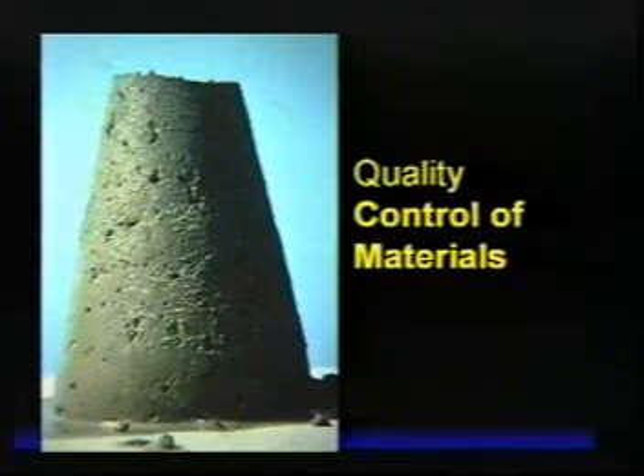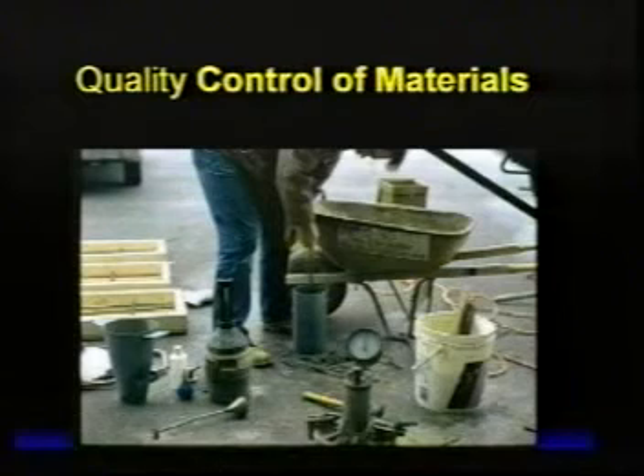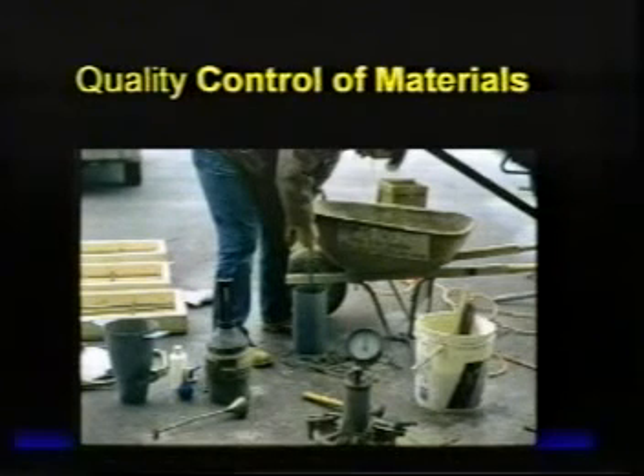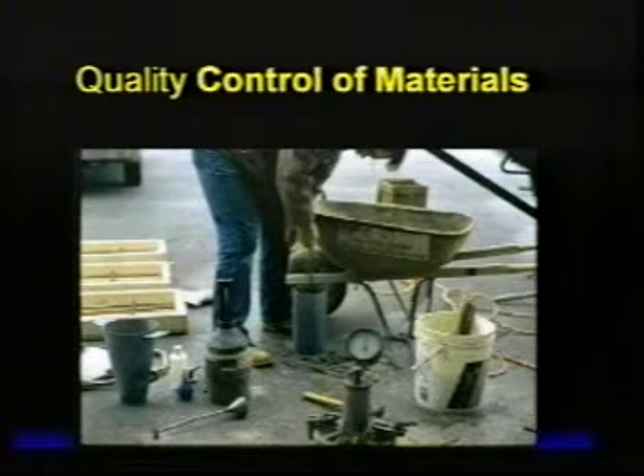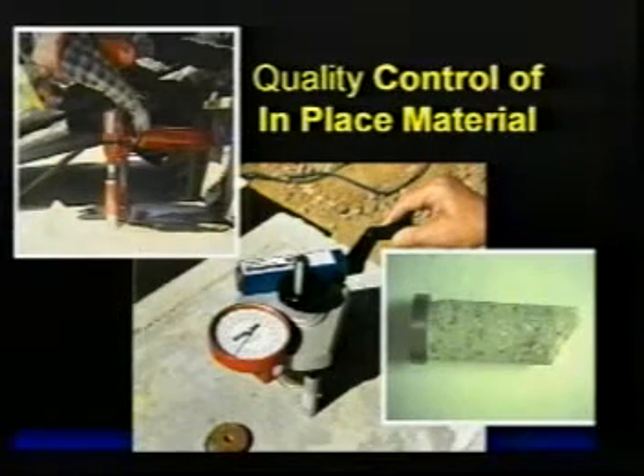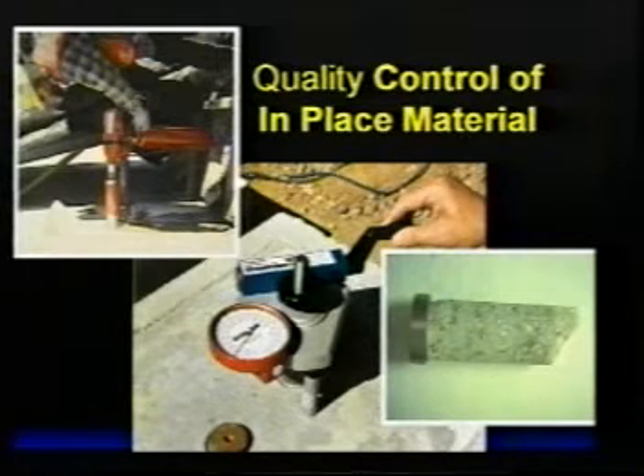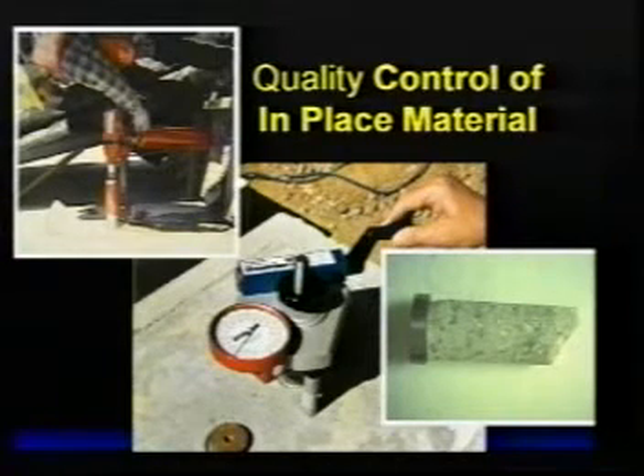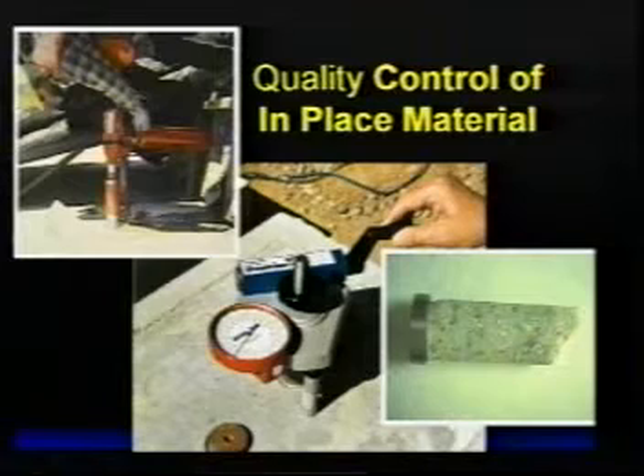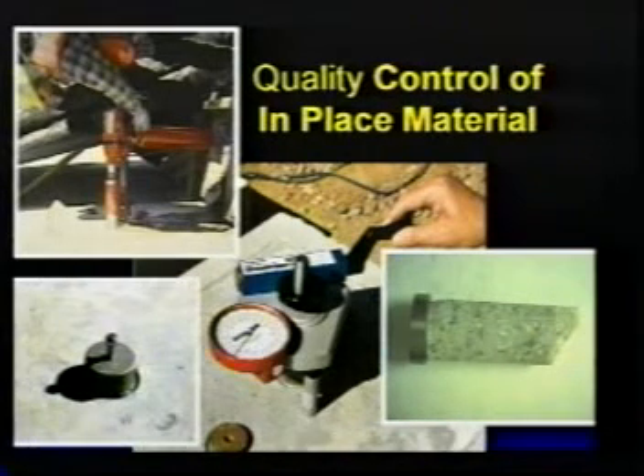So let's talk about quality control systems for all three of these methods. Obviously, we're looking for the quality control of the material itself. And basically, the recommendation is to follow all the same things we do for new construction, whether it's slump, air, cylinders for compressive strengths. These are all basic standard formats, and it's for prepackaged materials and also for the ready-mix type materials. The other aspect that makes repairs special and different from new construction is you're making a new type of material. You take a repair material and an existing material, you're making them as one. So you want to check the quality control of the in-place system, which is a bond test.